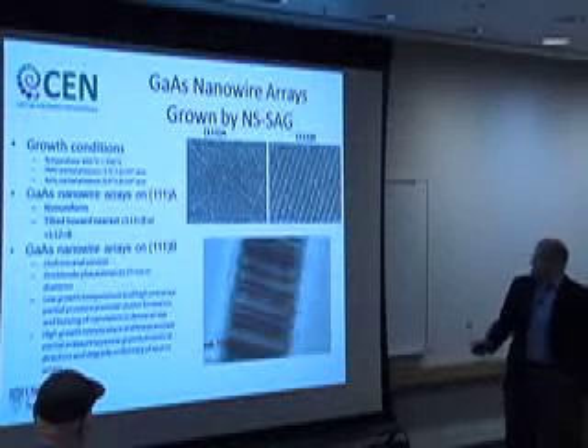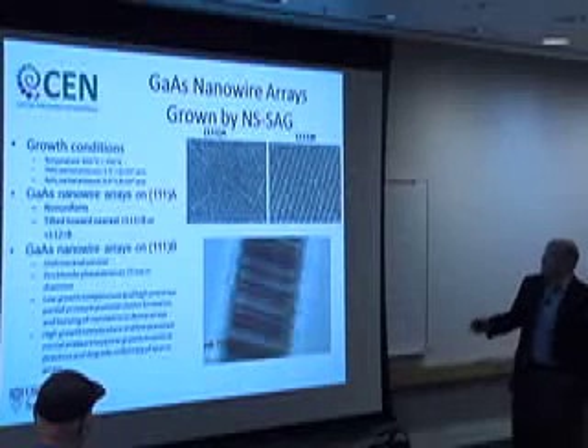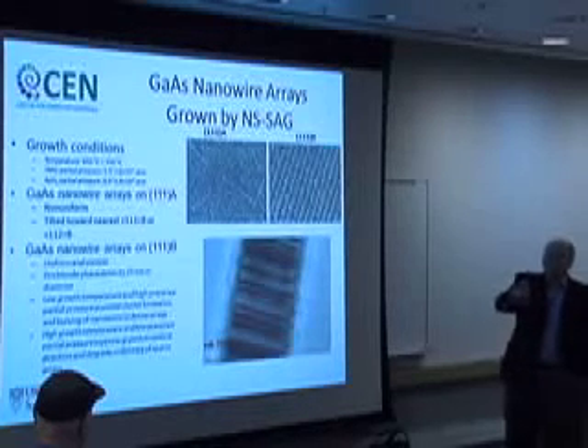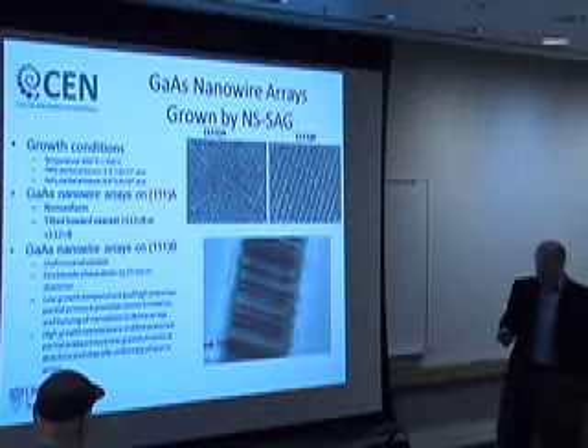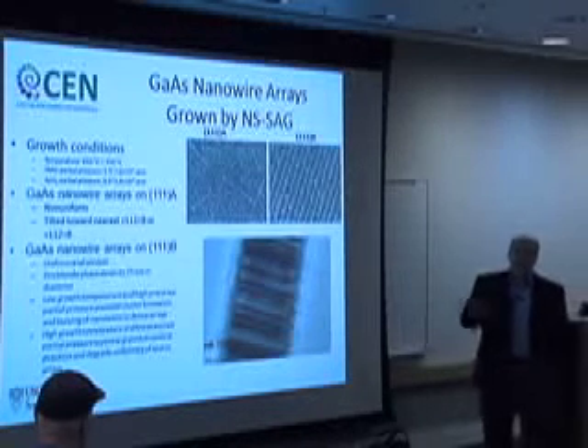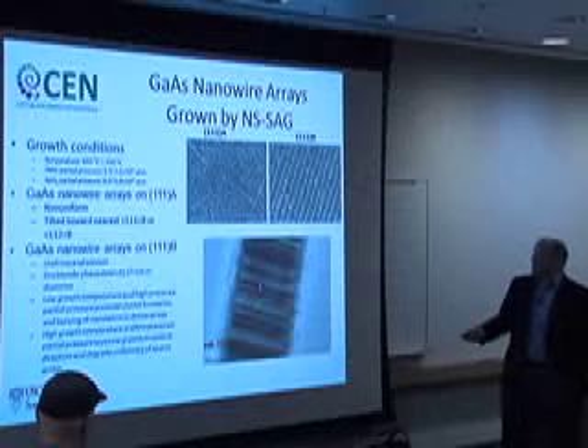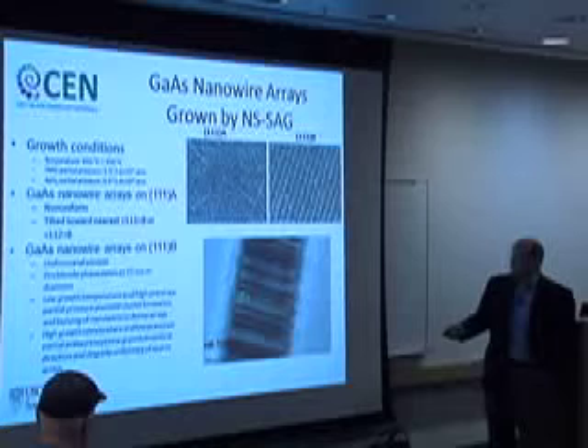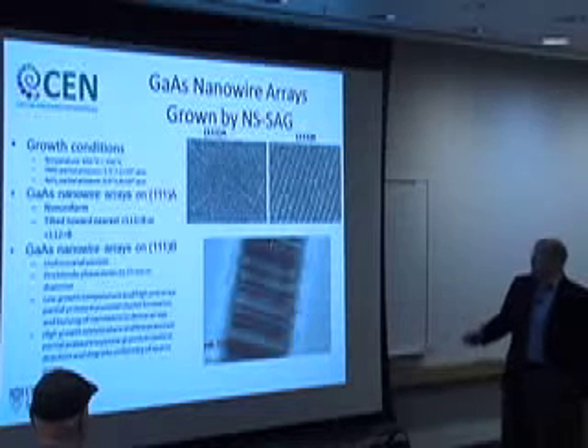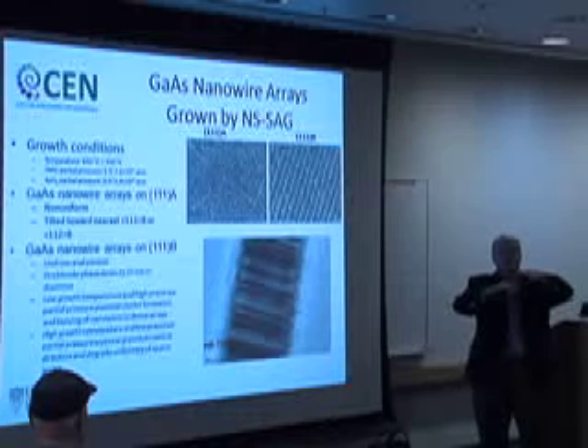One of the consequences of this way of growth is that if you look in cross-sectional TEM at these nanowires, be they gallium arsenide, indium arsenide, gallium phosphide, any of these materials, also grown not only by selective area growth but also by VLS techniques, what you find is there is a very dense array of stacking defects. And in some cases, there's actually mixed phases here, where some of these layers are wurtzite and some of them are zinc blende. In the case of most of the materials that we've talked about, they're all wurtzite materials, except that the crystalline symmetry rotates by 180 degrees at a twin plane.